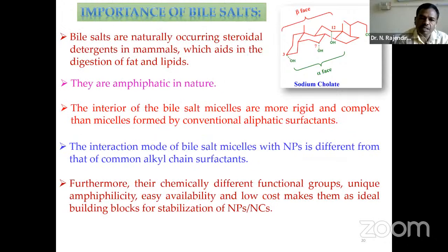Why is bile acid so important? In traditional surfactants there are many reports available for the synthesis of silver and gold nanoparticles, but for bile acids no one had reported. We reported it for the first time in the year 2009, and subsequently we made a lot of reports on this. Why it is so important: bile salts are natural. Another thing is that in ordinary surfactants, either CTAB or SDS or Triton X-100, we need to add some external reducing reagent, whereas in bile acids we need not add any external reducing agent because of the availability of reducing functional groups that are responsible for the reduction of metal salts. Also, bile salts are naturally occurring steroid detergent molecules, which aid the digestion of fats and lipids.